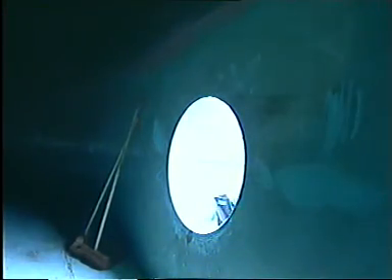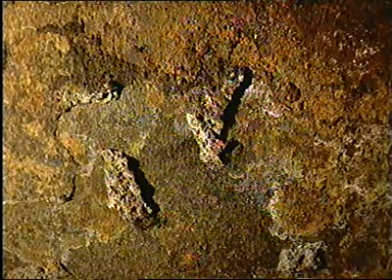At an earlier inspection in 1991, severe corrosion at the bottom plates had been found. In several places, the plates were near to perforation. This had been caused by acidic water collecting in the tank bottom. Water in the gas oil and from roof condensation had sunk to the bottom, picking up acidity from the oil on the way. This had led to a critical situation. Several bottom plates were replaced, but the problem remained. How could the corrosion be stopped?